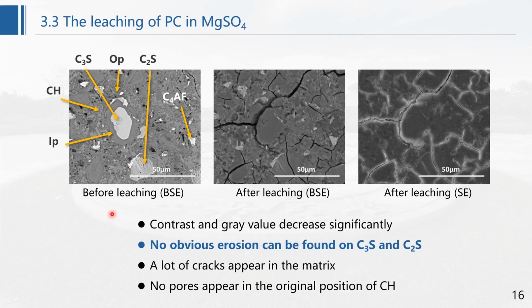Here are the BSE images of PC before and after leaching in magnesium sulfate. Here is the image before leaching and here is the image after leaching. We can see that after leaching, the contrast and gray value of the BSE image decreased significantly, which is more obvious than the previous groups. Different from that in deionized water and sodium sulfate, no obvious changes can be found on C3S and C2S. However, a lot of cracks appear in the matrix after leaching.